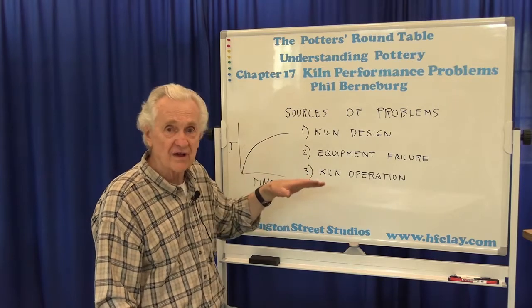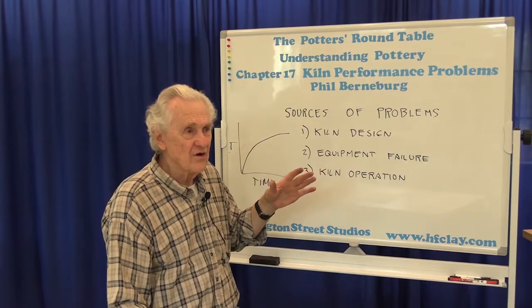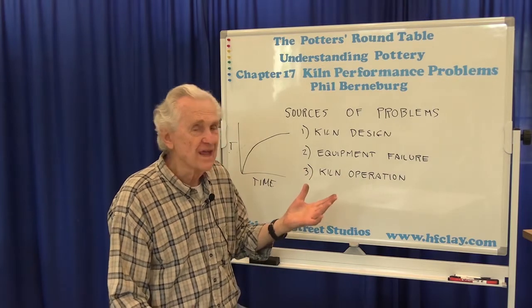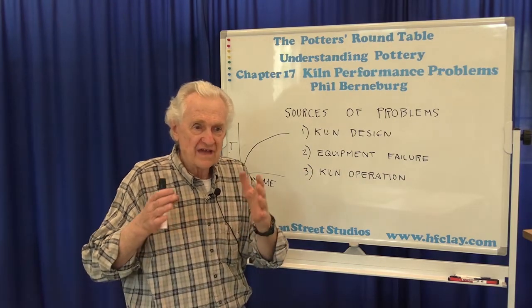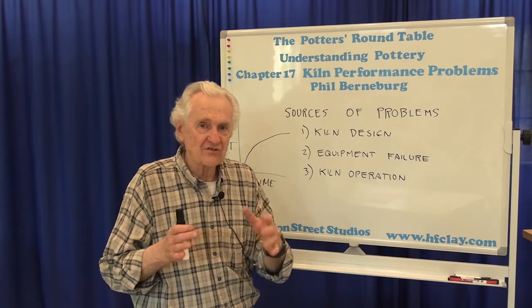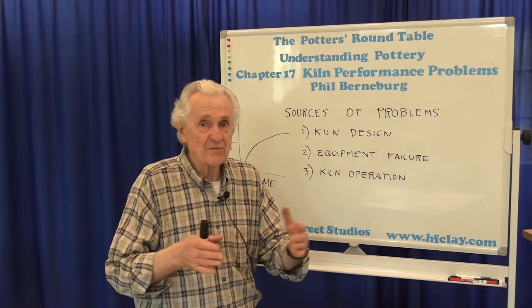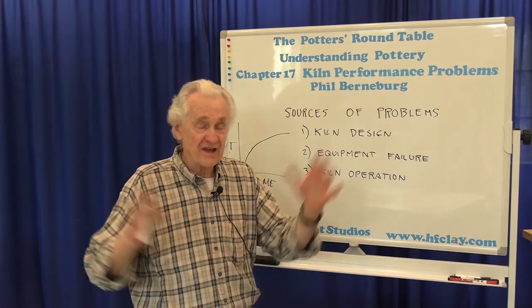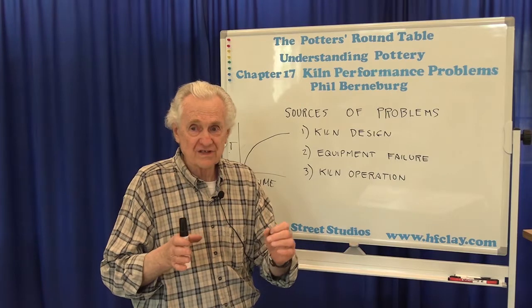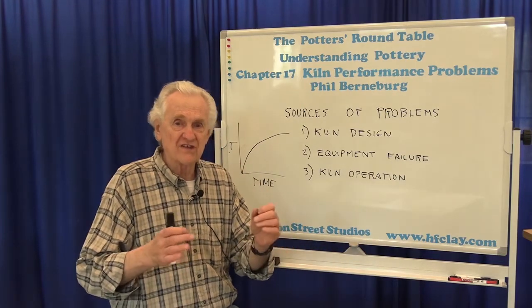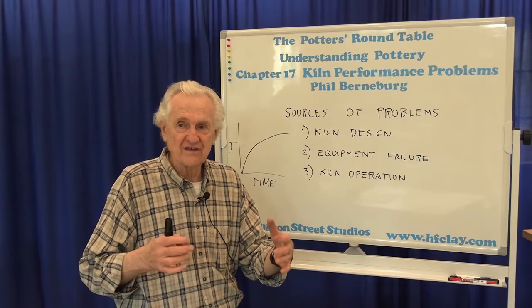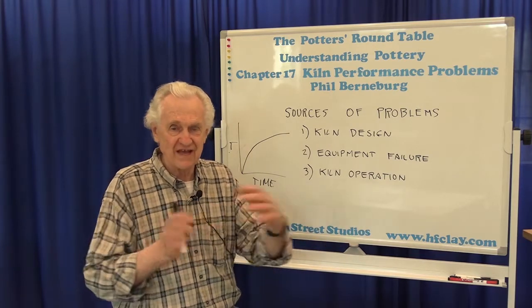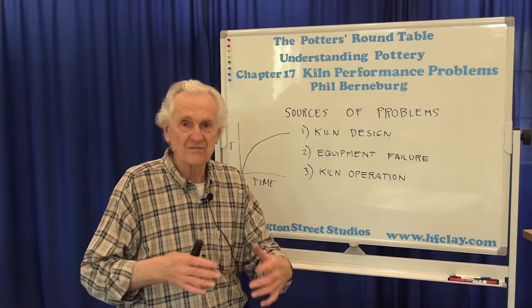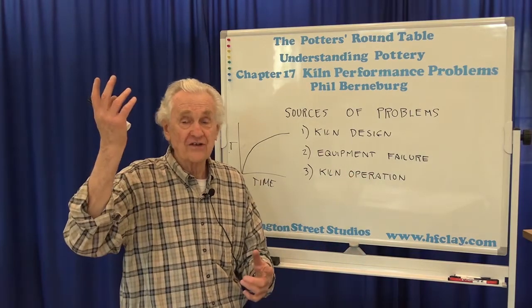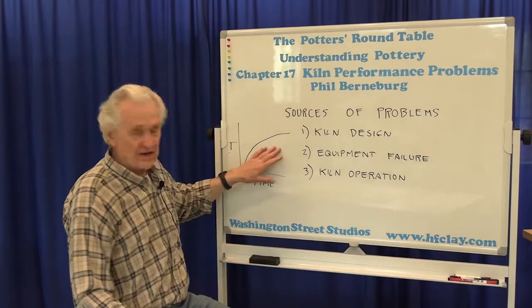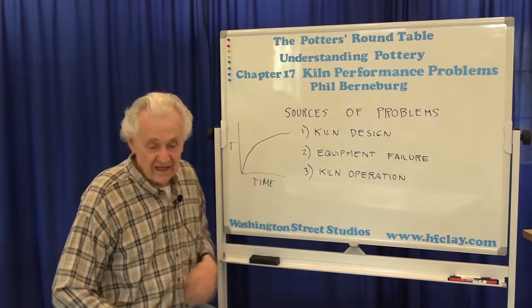Just as an aside, by the way, if you've ever wondered how efficient a wood kiln is, or even a gas kiln, in terms of how much of the energy, the heat, or the fuel that I put in actually goes to heat up the pots, it's in the neighborhood of 5%. It might be as high as 8%, but typically it's around 5%, give or take 2%, which means that 95% in round numbers of the heat that you're putting in, 95% of the wood, 90% of the gas, is doing nothing but heating up the shells, heating up the kiln, and going up the exhaust. So there's a lot of opportunity for heat to be lost, and you have to make sure you're putting it in fast enough.